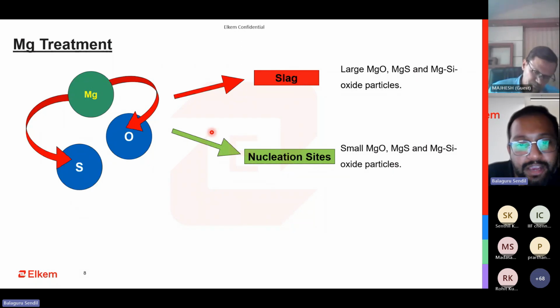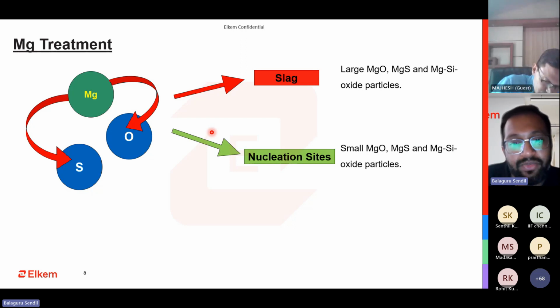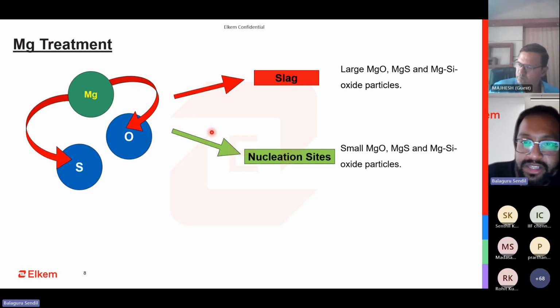How does the size keep growing? If you are holding the metal for longer after treatment, the size keeps growing. The nucleating sites accumulate together, float out as slag and then go out. That is why you see a gradual fading effect from the start of pouring towards the end of pouring. So this is what happens if you have magnesium that reacts with your sulfur and oxygen. It forms these nucleating sites of MgO and MgS.